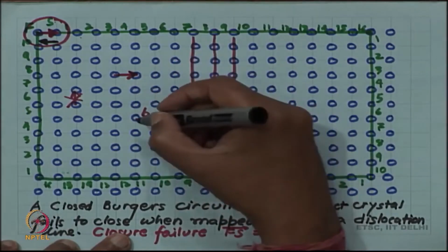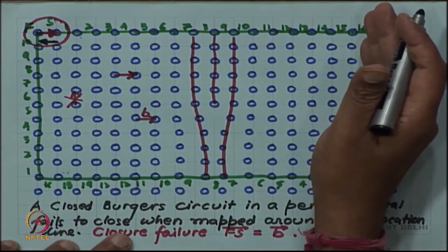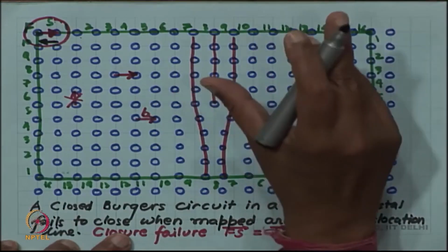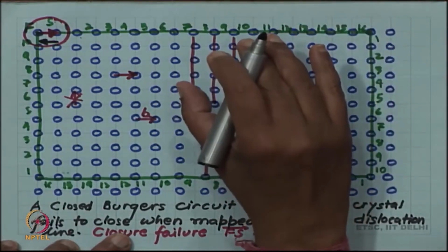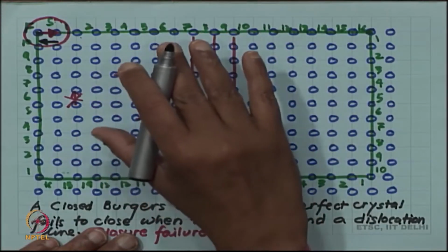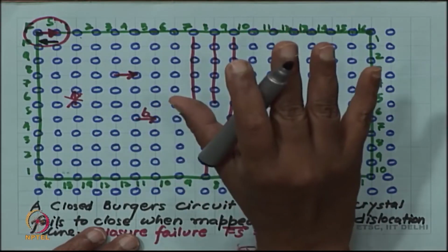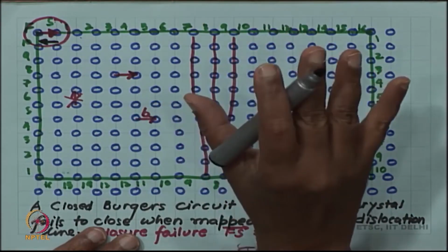This is because in the slip approach also, the magnitude and direction of the slip is not uniquely defined. Whenever there is a slip, there is a relative slip. So, the upper part of the crystal is slipping with respect to the lower part across a slip plane. If we look at the motion of the upper part, that will be in one direction.